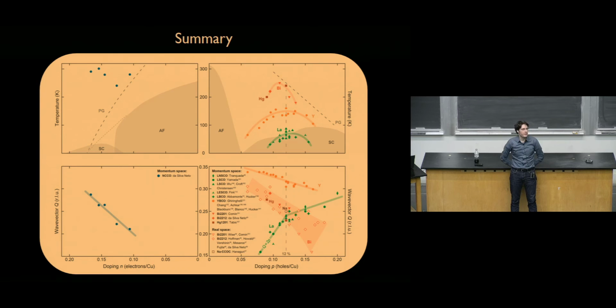We're thinking of doing some devices where we inject currents to suppress superconductivity, to get into the flux phase, or actually flux flow phase, I think it's called. So not quite into the depairing regime, but injecting electrical currents as opposed to using a high magnetic field to suppress superconductivity, and see what the impact is on charge order. Unfortunately, you have to get to very high magnetic fields to do something dramatic to charge order. You have to go above 16 Tesla, and you cannot do that with soft X-rays. You simply cannot do that.